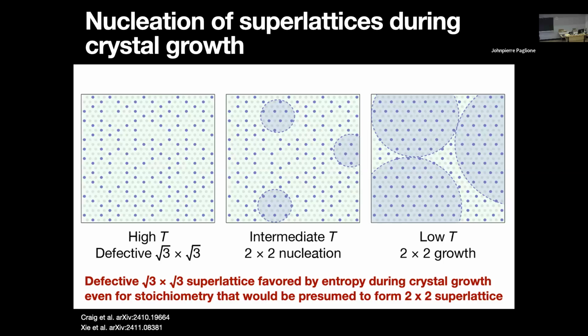There are lots of ways to arrange a stoichiometry of 0.25 in a root 3x3 structure because there are lots of vacancies. And so entropy favors this, and then as you're cooling, the hypothesis was that you'll start to nucleate the 2x2 domains, and you can then end up trapping root 3x3 domains between these 2x2s. So that's what the theory says. So let's see in an experiment.